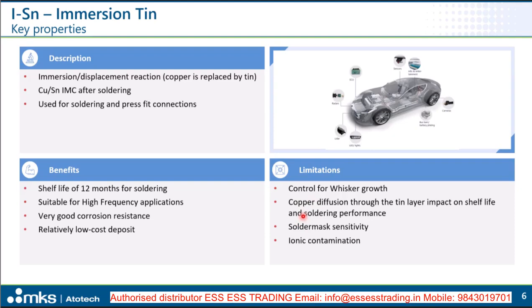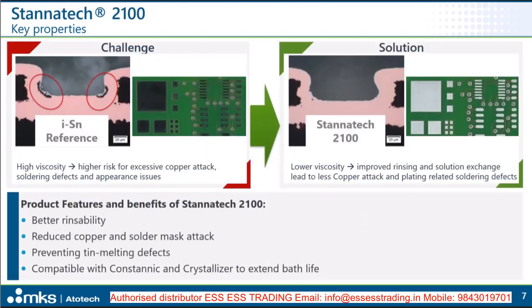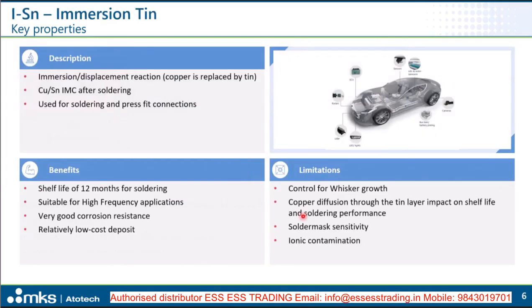And the immersion tin process is a very aggressive process, so it's highly acidic, and therefore there is at least a certain risk that it attacks the solder mask, and in particular if solder resists are not properly applied or are not well cured, then there might be an interaction between immersion tin and the solder mask which is not beneficial and which leads to defects of the final finish afterwards. We will come to this later on as well.